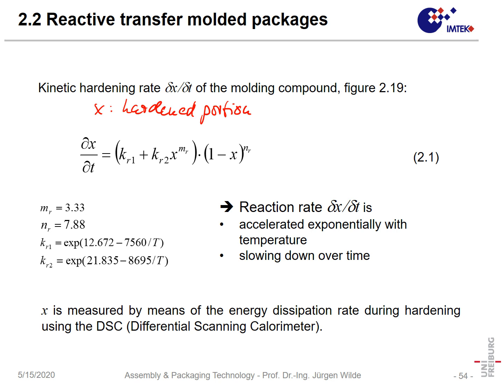So if that x is low, that factor 1 minus x here is 1, then we have a high rate, but if we have hardened already 50%, then this is only 0.5, and that means this hardening rate will decrease. That's one effect. So the reaction is slowing down over time. And the other effect is what we have seen. We have an exponential increase with temperature.